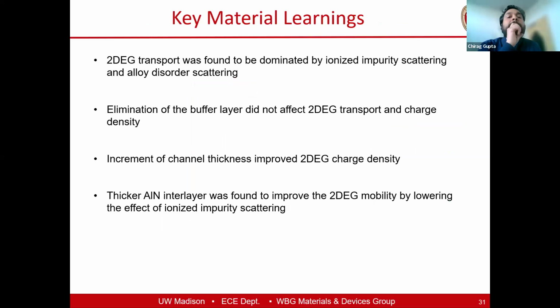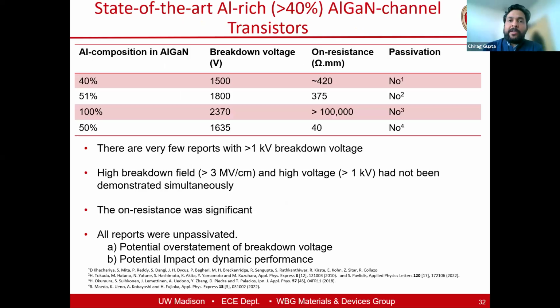So the key material learning that we have had so far is that alloy disorder scattering is really hard to get rid of. We basically need to make sure that we optimize our channel deposition in the best possible way to give us the highest possible mobility in these layers.